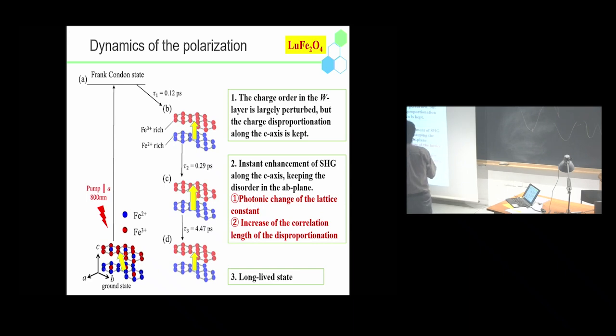This is a summary of the anisotropic polarization of lutetium Fe2O4. This is the ground state. We irradiate the 800 nanometer pulse. Then, at first, we observed this. In the first stage, the charge order in the W layer is largely perturbed. So this is a decrease of the SHG along the ab plane. However, the charge disproportionation along the c-axis is preserved. This is the reason why the c-axis component is not so changed. Second, we observed the instant enhancement of SHG along the c-axis, keeping the disorder in the ab plane. As for the origin of this second stage, we cannot conclude a definite scenario.